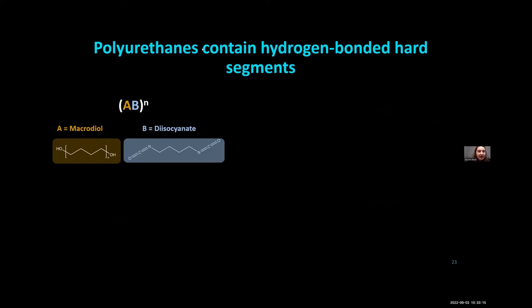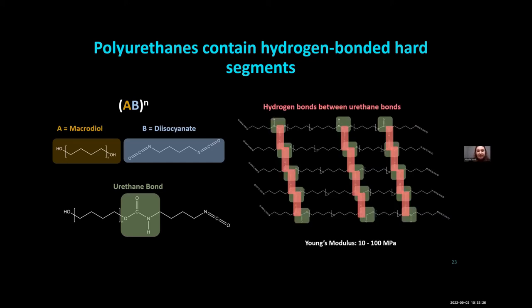Polyurethanes are unique because they have essentially two blocks in them: a macrodiol component and a diisocyanate that are reacted together to form a urethane bond. These urethane bonds can hydrogen bond with each other across these chains, forming physical crosslinks. In this way, the material can behave like an elastomer. Unlike a silicone that has chemical crosslinks, allowing it to stretch and go back to its original configuration, a polyurethane has these physical crosslinks whereby you can stretch it and it will return, but you can design it to be melted as well. And they have a Young's modulus in the range of the eardrum.